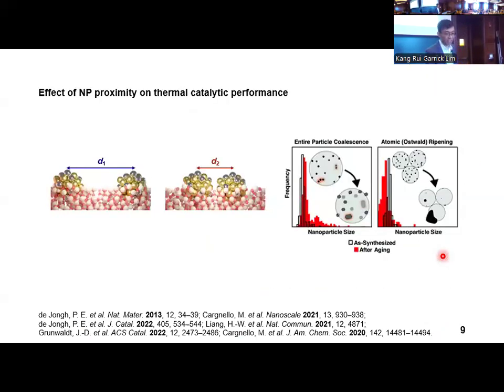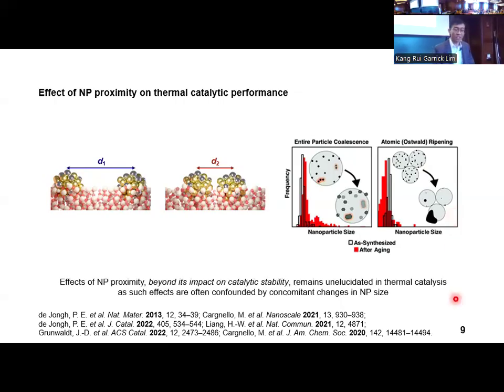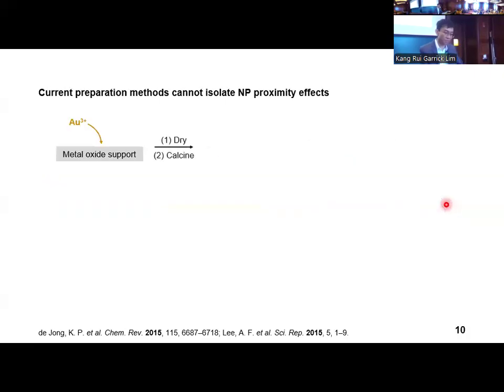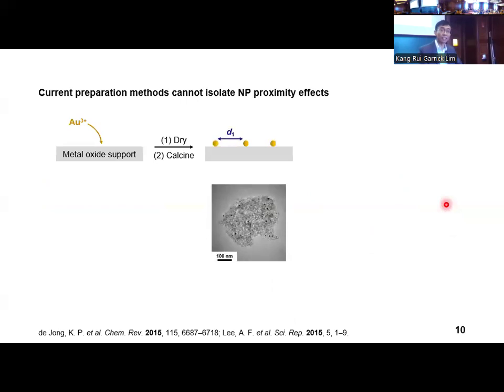When we consider thermocatalysis, the effects of nanoparticle proximity is primarily centered around stability, with shorter interparticle distances resulting in nanoparticle aggregation and growth. Beyond its impact on stability, we could not find sufficient literature on the direct impact of nanoparticle proximity on other thermocatalytic performance indicators, such as activity or selectivity, without being confounded by accompanying changes to the nanoparticle size distribution.